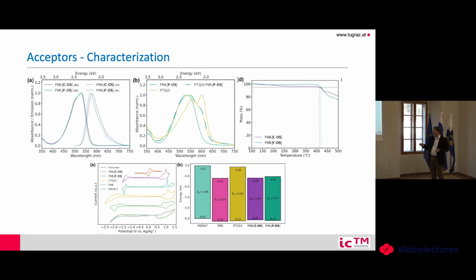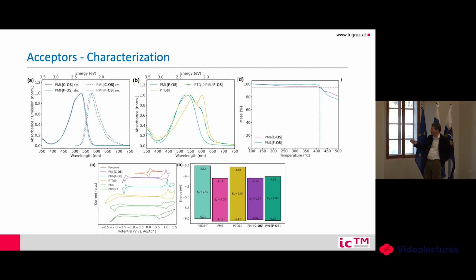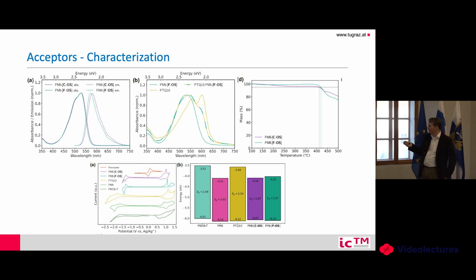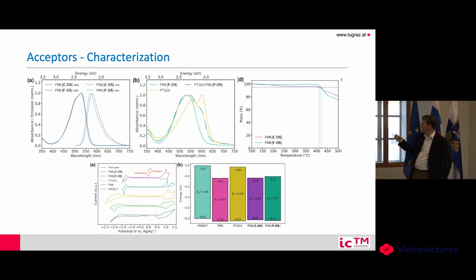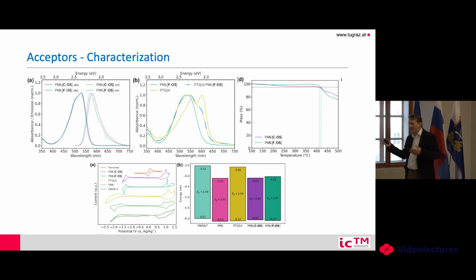Then of course we have to determine the optical properties. So we have to measure the optical spectrum, usually the fluorescence in solution and in thin film. We measure the thermal stability, and we also measure by cyclic voltammetry the oxidation and reduction of the material, the HOMO-LUMO level. So we do a lot of characterization, but we have not built any solar cell with this material yet. Although the synthesis is quite easy, we need at least 3-4 months before we can even start to build a solar cell.